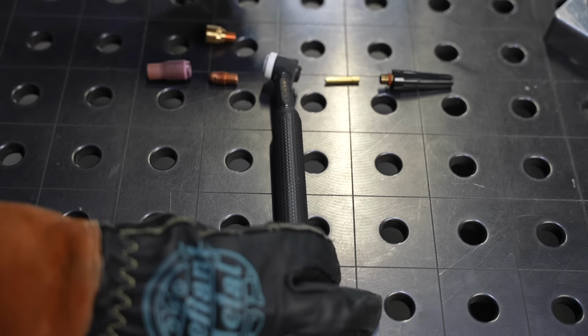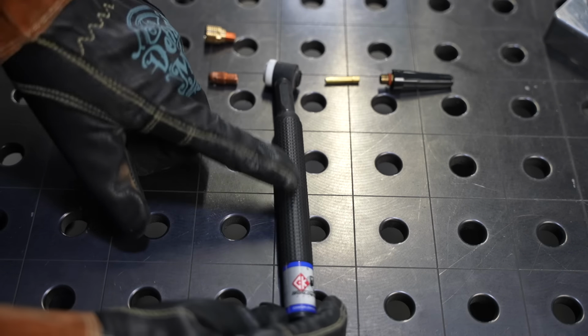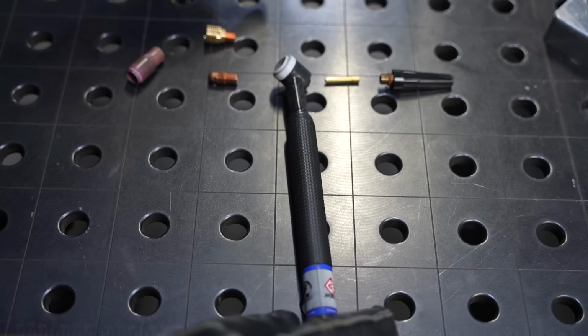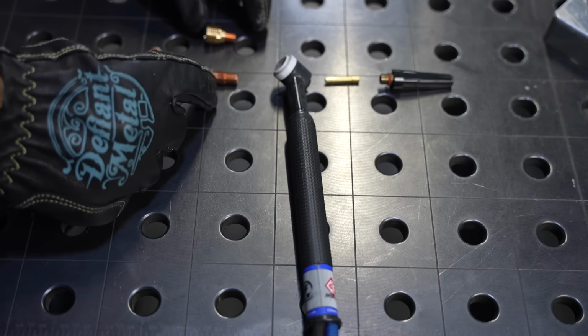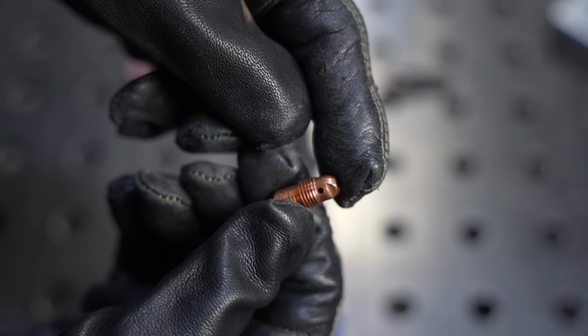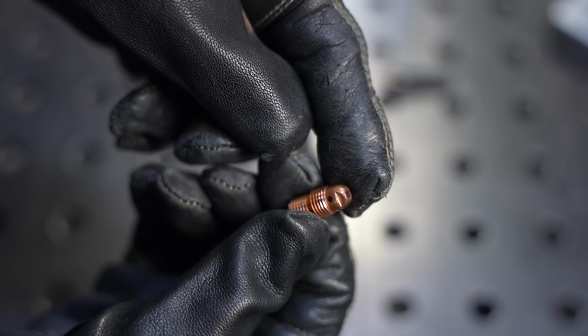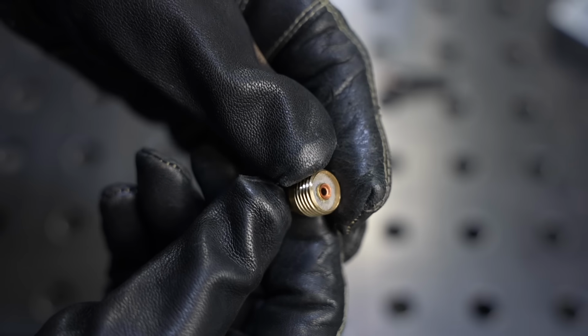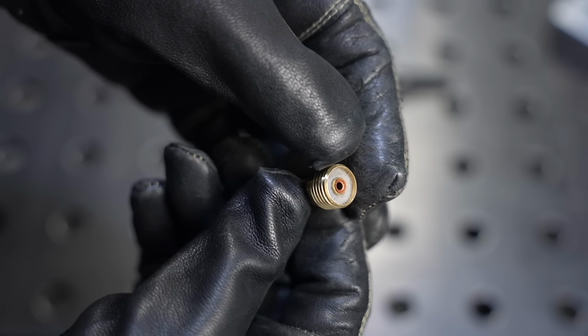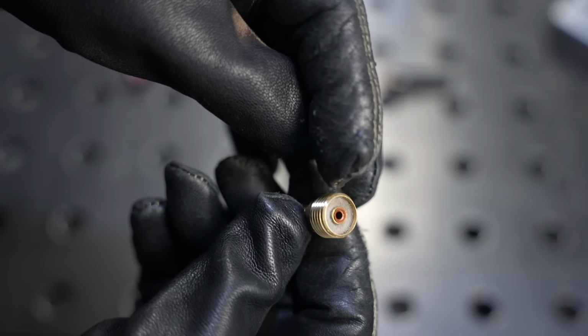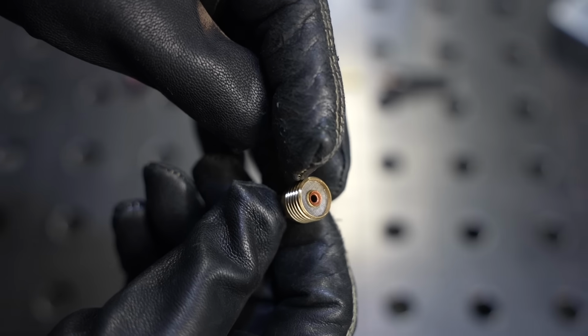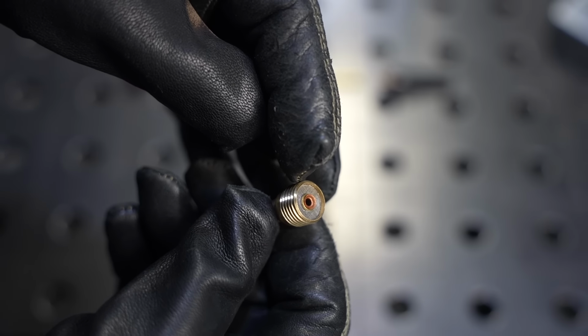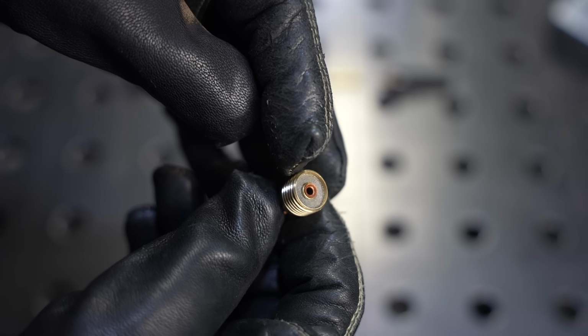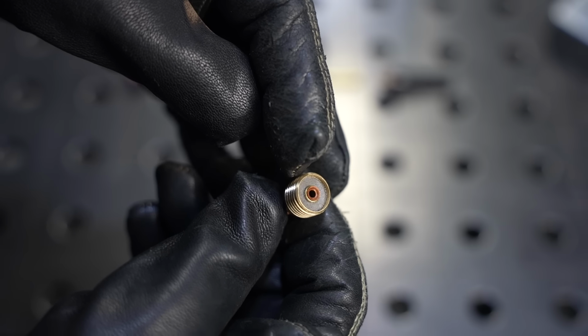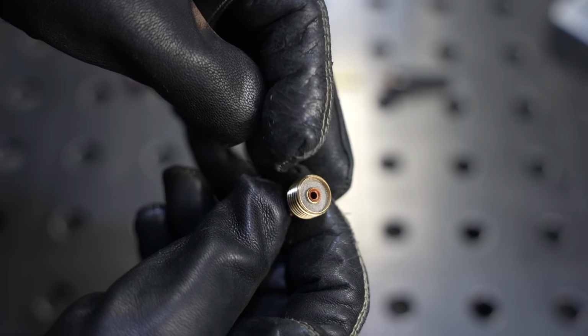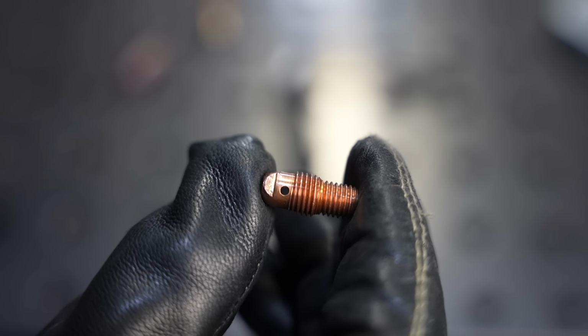So this is my torch body. These come in different sizes, but with any of them, you can get two different types of collet bodies that actually hold your tungsten in place. This is a standard collet body, so it has those holes on the outside for gas to come through. This one right here is a gas lens. It has that diffuser there to give you a steadier flow of gas. This is a huge benefit on stainless steel or titanium and even on carbon steel, but on aluminum, it really doesn't offer a whole lot of benefit, and the aluminum can actually spit back and start to plug up that diffuser over time. So I prefer to use a regular collet body whenever I'm welding aluminum.